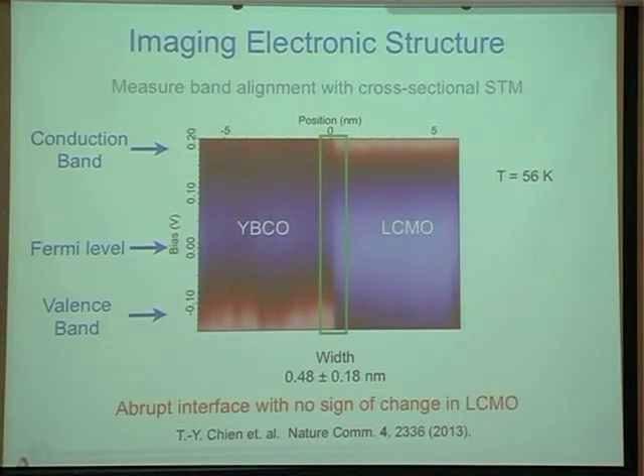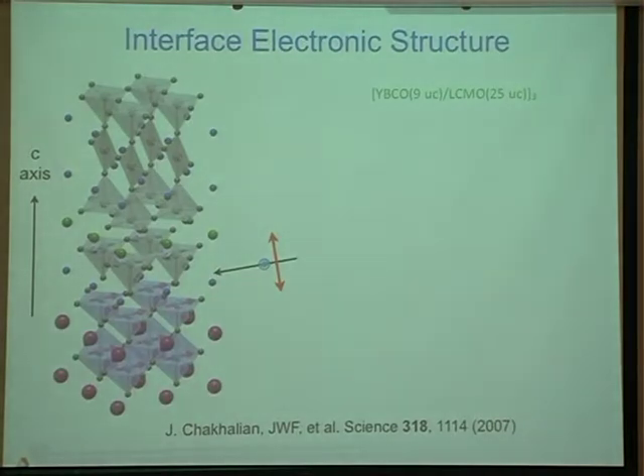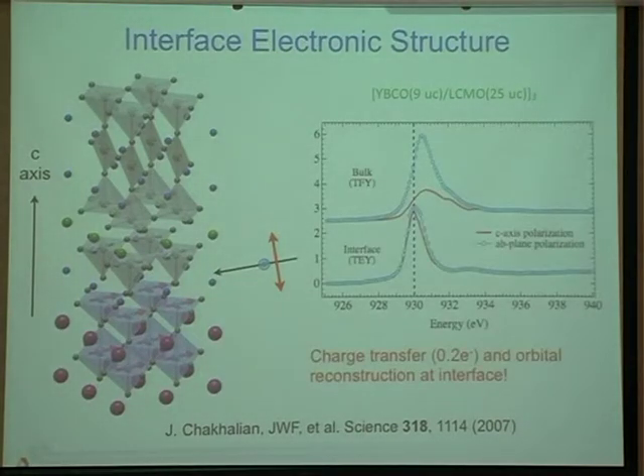And so what we found was this interface is actually extremely sharp. And I didn't think I would have time to go into it. We've actually been doing spectroscopy in ultra-thin structures. And this is very consistent with the fact that this phenomenon that I showed you here, this interfacial orbital reconstruction, our recent data on very thin structures shows that this is really limited to that first copper-oxygen plane.